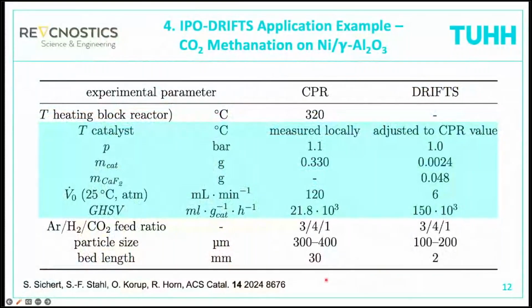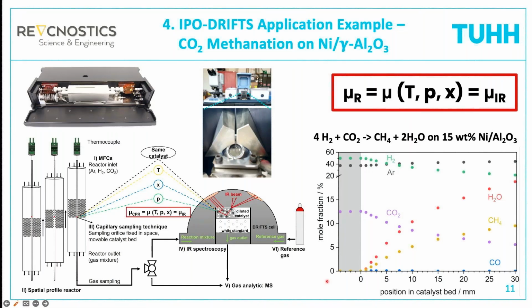Slide. So here, this was at the very beginning when we started to develop this isopotential spectroscopy technique, and we had only one Harrick cell in the lab. This is what I had in my lab in Hamburg. So we used this cell and first performed the isopotential run on the diluted catalyst. But then we have to do the same isopotential run on the pure diluent, which is calcium fluoride. What we had to do is take the cell out, open it, take the catalyst out, put the diluent in, put it back in, start everything again.